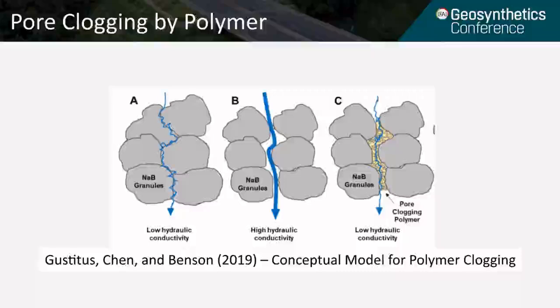When we start talking about the results, we want to give you a conceptual model for polymer clogging, which is our hypothesis on the mechanism of the BPC GCLs. As we mentioned, sodium bentonite is chemically sensitive to the leachate. When you have a dilute leachate, you will often see the sodium bentonite granules swollen, and you have low pore spaces for the flow to occur.